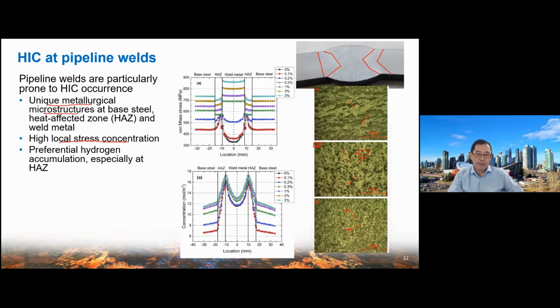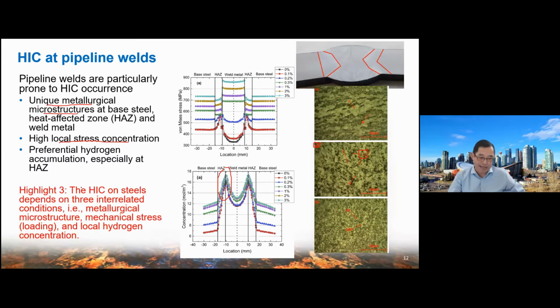Number 3, in the welding area, depending on the different conditions, there is always a hydrogen accumulation. You can also see from this figure that we found the hydrogen concentration has a peak at the HAZ and the interface between the HAZ and the welded metal. So let's come to highlight 3.